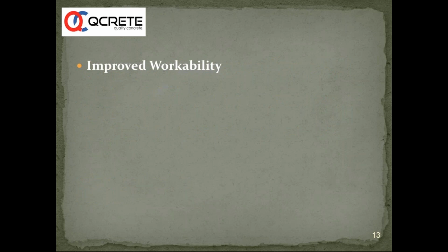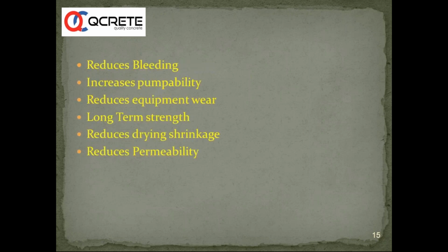So we talked about the sphericity of fly ash particles. Because of the spherical nature of these fly ash particles, you get improved workability. This is one of the biggest advantages that we get while using fly ash. Anybody who has made concrete with fly ash and without fly ash can easily appreciate that fly ash concrete has less segregation and less bleeding. So the benefits, as we can list, are that it reduces bleeding and increases pumpability, which is very good for a concrete producer. And another advantage for a concrete producer is that it reduces equipment wear and tear.